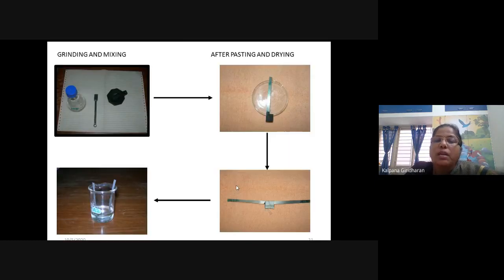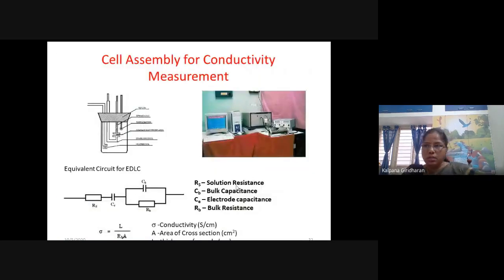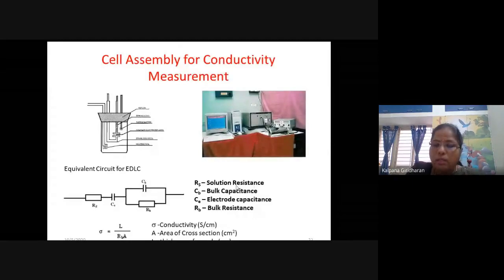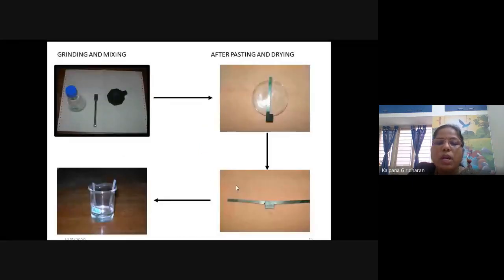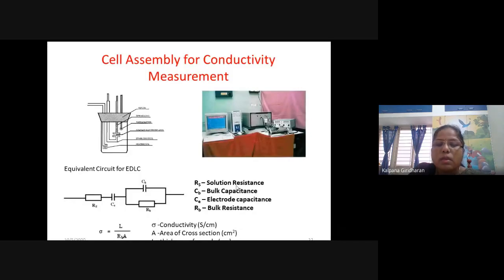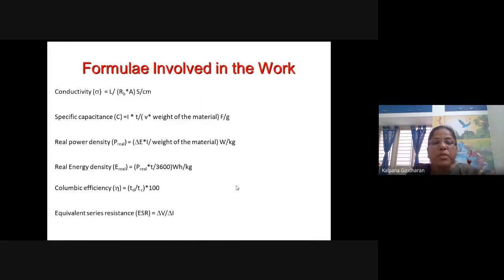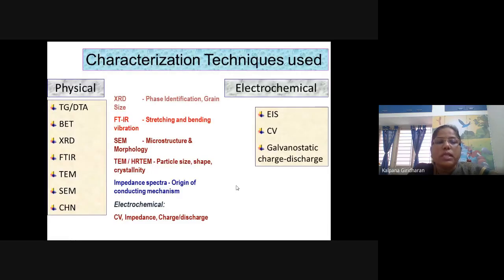So this is the lab scale technique, how we prepared a supercapacitor as a device. There are many conductive diagnostic devices to characterize it physically and electrochemically. This is a well-known conducting measurement. We used a workstation, and we can find out the solution resistance, bulk capacitance, electrode capacitance, bulk resistance from this Nyquist plot, and the conductivity can be obtained from this equation. So this is the formula we used in this work. These are the physical characterizations and electrochemical characterizations we have used.